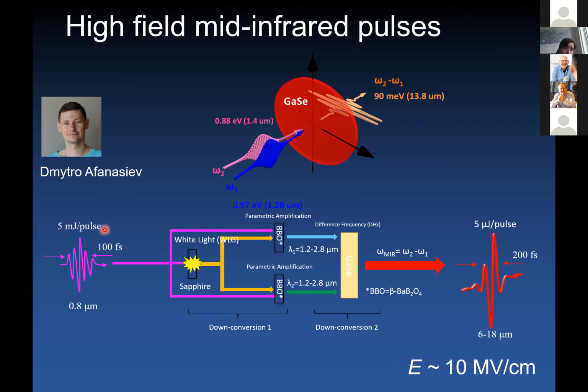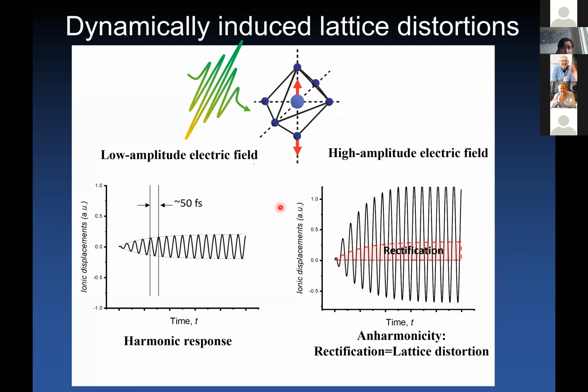And so note that we pay a large price in order to produce this field. So the energy efficiency here is not great. So we start from 5 millijoule per pulse here, and we get 5 microjoule per pulse at the end. But still, this is enough to produce electric fields that are significant and can displace atoms out of their equilibrium positions. So why do we need them to be strong?